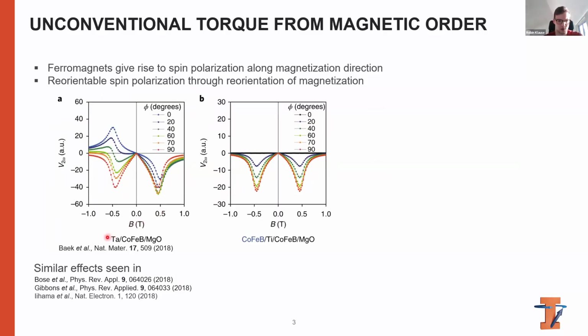This has been shown here, where on the left they have tantalum, cobalt iron boron, which is just a spin source and ferromagnet like before, and they compare this to a ferromagnetic trilayer with titanium in the middle. They see differences in the spin polarization and the resulting spin torques, and there are other papers where similar effects have been seen.